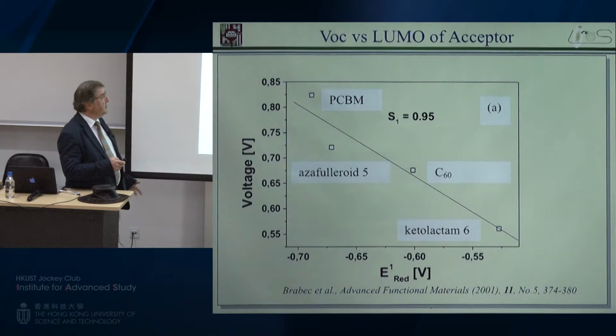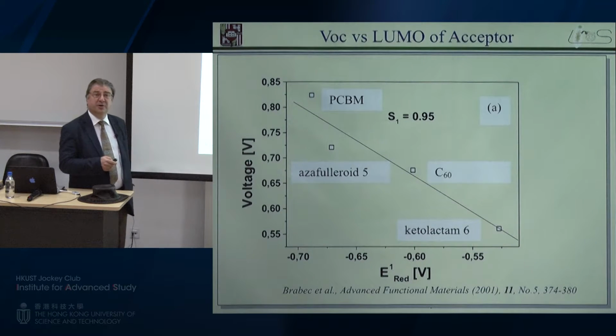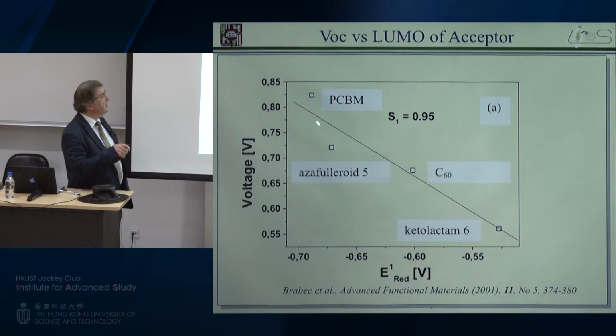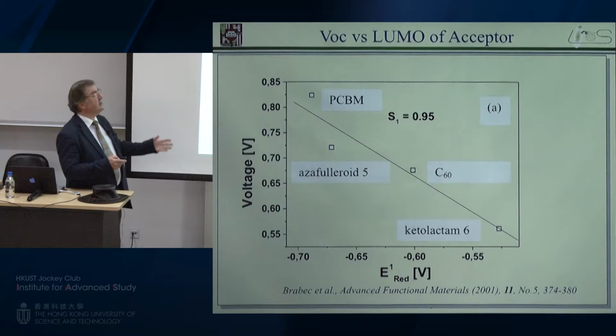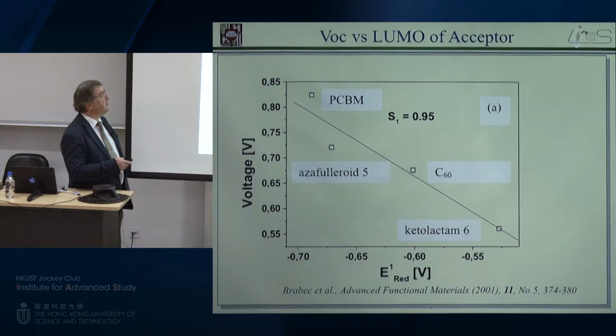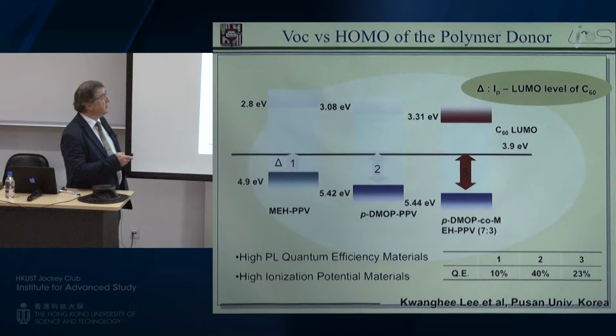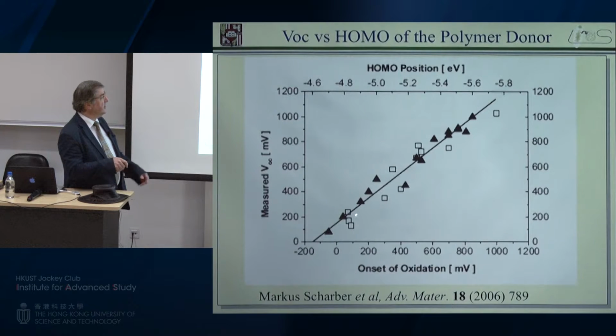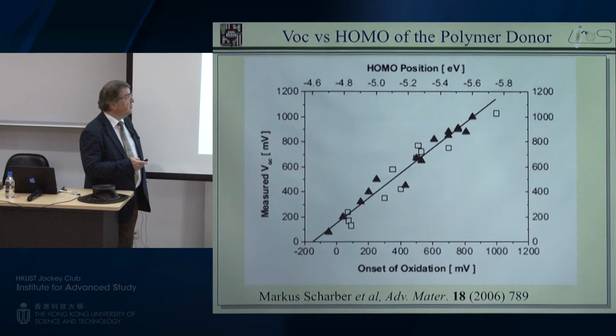And we checked it experimentally by manipulating these HOMO-LUMO levels with different substances. Indeed, with different C60s, for example, the first reduction potential, which is the LUMO level, and the open circuit voltage go nicely linearly together. The same thing also holds for the first oxidation level of the polymer donor. All these points are different materials, but they all line up beautifully. So that concept seems to be also working.